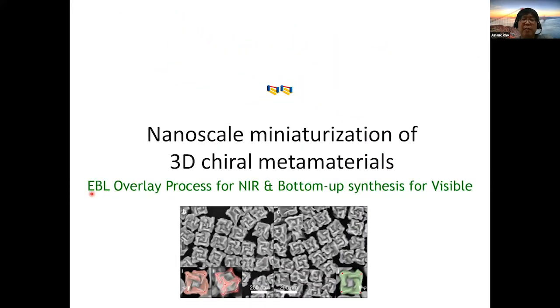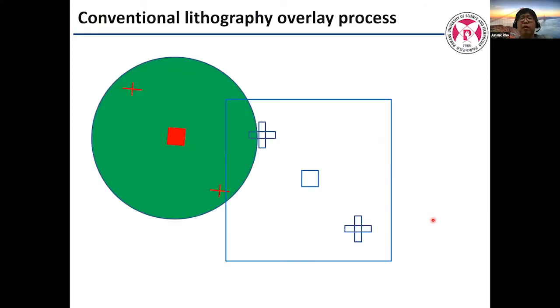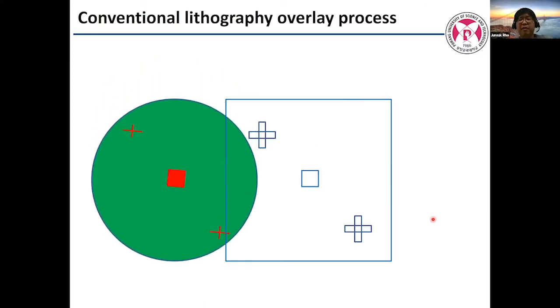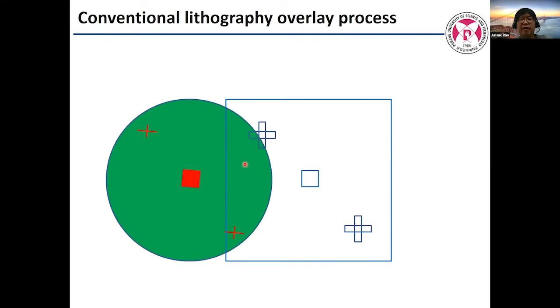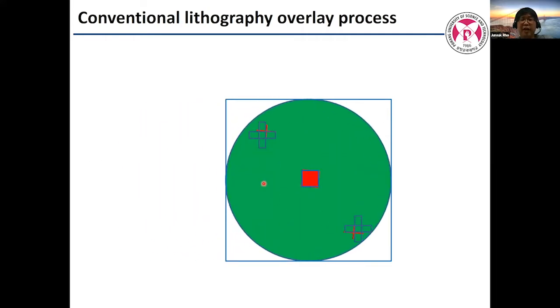So I will show two examples. One is using e-beam lithography overlay for near IR chiral metamaterial, and then bottom-up synthesis for visible chiral metamaterial. So this is what happened in microfab. This is the second layer mask, and this is the first substrate. The pattern is done, but the alignment is not good. So we do rotation and translation to make the alignment okay. So we can see the alignment mark. So good exposure. So go on.